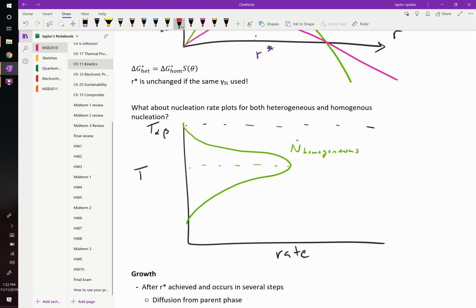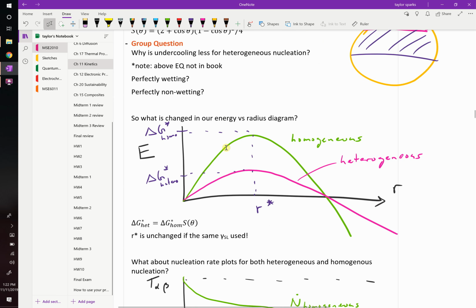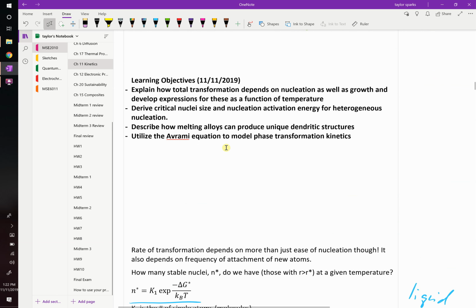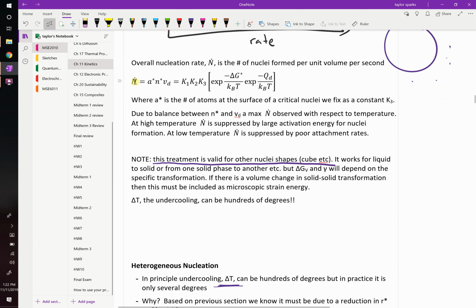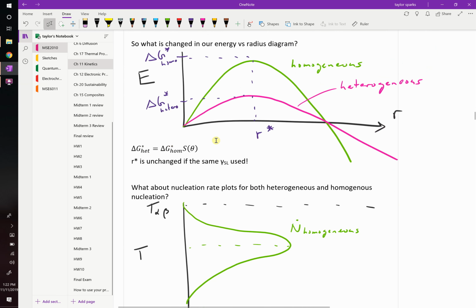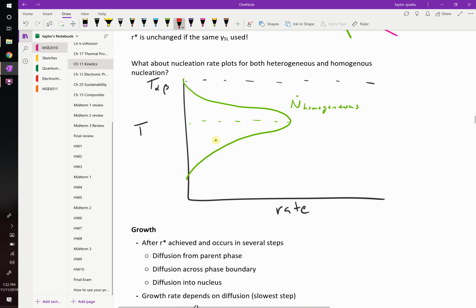How's that going to look different for heterogeneous? How ought we to modify that? Well, we could go back to our expressions for the nucleation rate, capital N dot. It depended on a bunch of constants. Let's assume those constants are the same. Fair assumption, same material. All we've done is change the nucleation type. Then you've got your activation energy and diffusion. Diffusion should be exactly the same, but instead of negative delta G star, in the heterogeneous case it includes that S of theta term, which is between 0 and 1. So it's going to look exactly the same, except we're lowering the activation energy. So what we should see is that heterogeneous nucleation should look like that.